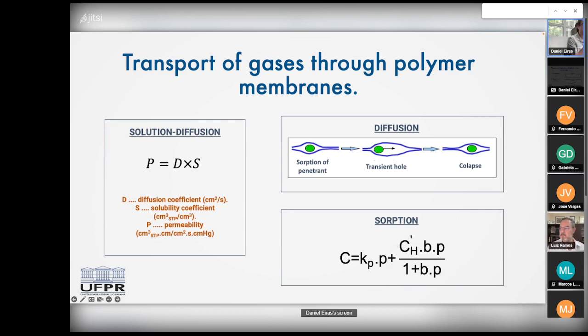So usually the gas molecule is absorbed by the polymer. Then a transient space, or a transient hole, is created inside the polymer membranes by the movement of the polymer chain. This creates the space necessary for the gas molecule to jump from one sorption site to the other, and after that, this space collapses and another space opens, so diffusion can continue. This mechanism depends a lot on the flexibility of the polymer chain and the fractional free volume. Those are two aspects that we try to control when we modify polymer materials.